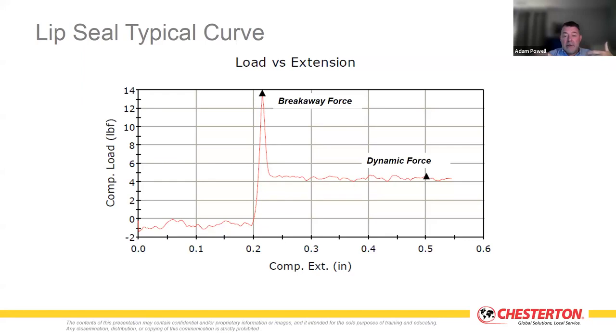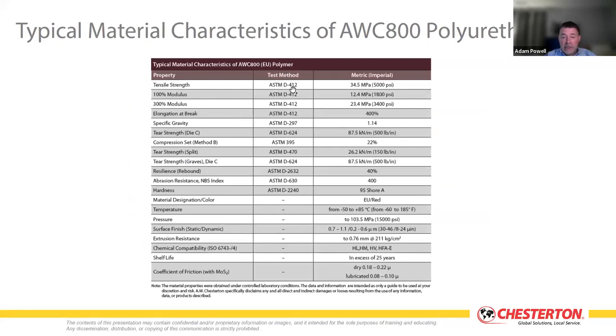So you're really in a situation where you've got this seal that's putting less load on itself, providing adequate sealing, with a wide range of dynamic capability and a relatively low load through its operating life, resulting in a longer operating life. So these are all pieces that we have explored over the years and fed back into the designs. This is a little bit of a data sheet. It is the data sheet on AWC 800 polyurethane, all done with standardized testing and the resulting data. Essentially, it's a high elastic memory, hydrolytically stable, and very abrasion resistant.